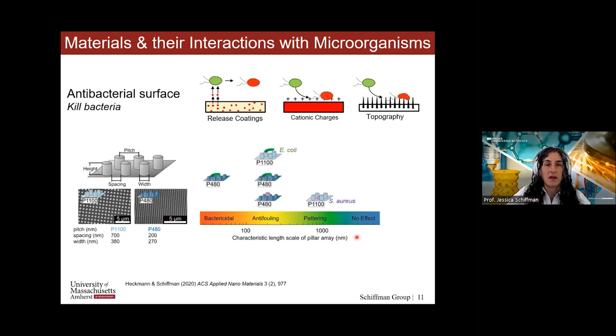And so since we started off talking about antibacterial, we can look here and see that our E. coli, which are rod shaped, about 1.5 microns by 0.5 micron, well, they too die by our smaller pillars. However, when we look at some of our smaller structures, they do not kill as well. And actually, when we conducted two different assays, one where we looked at killing and one where we looked at anti-fouling or repelling, we saw that the same kind of structure could both kill or repel the E. coli. So this might be interesting. We can repel lots of E. coli, and the ones that do stick around get killed.